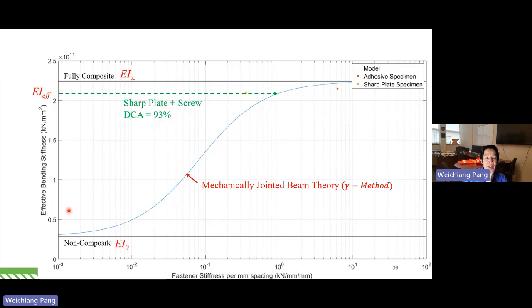About 93%. This is 0%, this is 100%, 93% of composite level. The adhesive plus screw is a bit higher, but they're almost the same, 95%. So based on our test here, we can conclude both of them almost achieve a very high composite level.